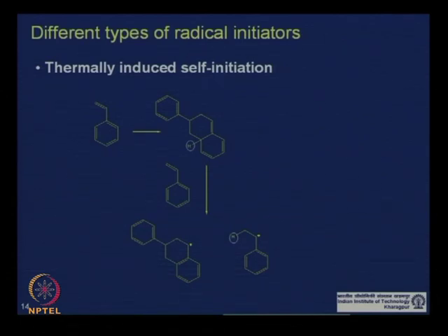proposed for thermally induced self initiation of styrene, whereby two styrene molecules by Diels-Alder coupling first get dimerized, and then this dimerized styrene molecule can react with a third styrene, which abstracts a hydrogen atom, forming two radicals which can individually initiate the polymer chains.